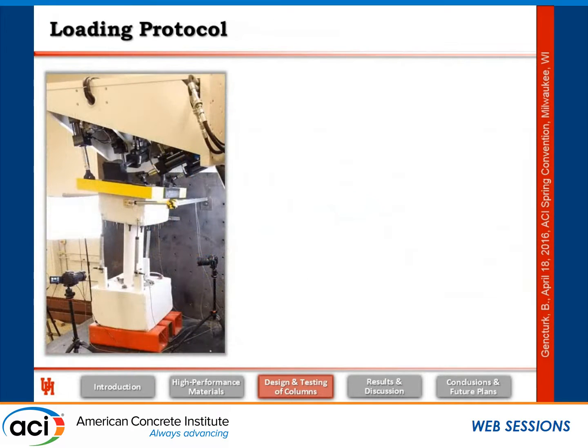We use what we call the LBCBs. Those are multi-axial loading units. So you see this yellowish platform here. It can move in all 6 degrees of freedom. And we can control forces and displacements independently. So we can do mixed mode control, like we can control the axial loading in force while the horizontal movement in displacement. So that's what we call the mixed mode control.